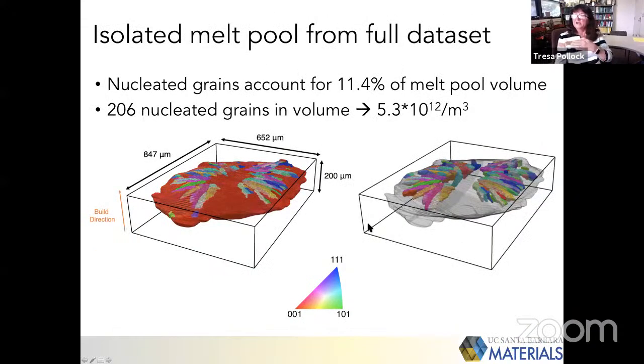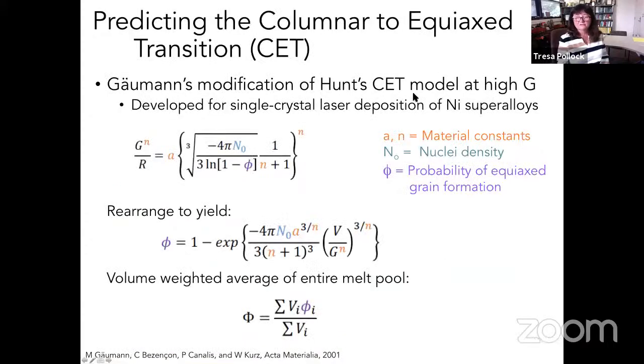And so given that we can very clearly define where that melt pool boundary was from the sections, we can now actually separate the entire melt pool from the rest of the structure. And so again, you see that all of the red grains have grown up from beneath due to remelting. And then we have all these grains on the surface which have nucleated independently. And so what this allows us to do, since we have the volume here, is actually count the nucleated grain density. And so in this case, the new grains that have nucleated account for 11% of the volume.